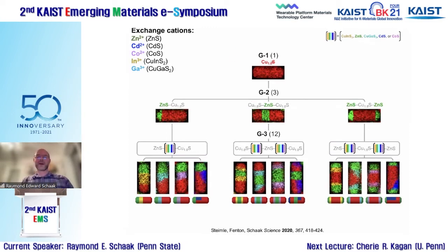And so starting with the copper sulfide rods, the first generation, Ben was really good at this and figured out how to install a tip of zinc sulfide, a central band of zinc sulfide, and a double tip of zinc sulfide. So we could make these three in reasonably high yield. We also realized we could make samples that contained all three of them so that we could microscopically sample without making quite so many samples. But long story short, these three are the starting materials now that we're going to see what all is possible.